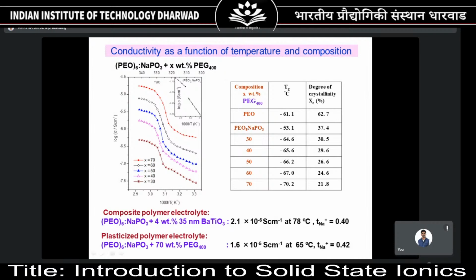Now you would have wondered why the transference number of sodium ion is 0.40 and not 1, isn't it? But here in this case, we have calculated both the electronic transference number and the ionic transference number. When we measured the electronic transference number, it was tending to 0, that is 10 to the power minus 4. There are different techniques to measure transference number. One of them is this particular AC/DC method, and in that case the transference number of sodium ion is 0.40, that means roughly 40%.